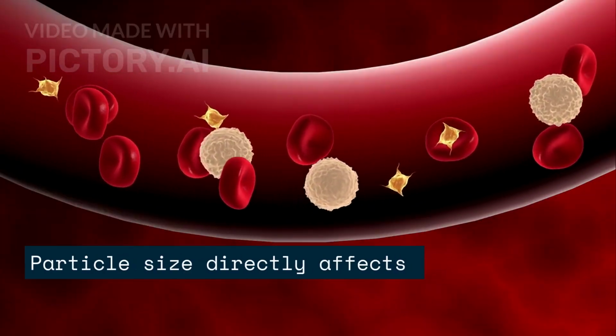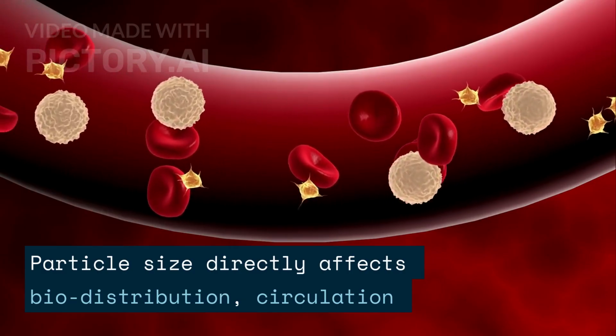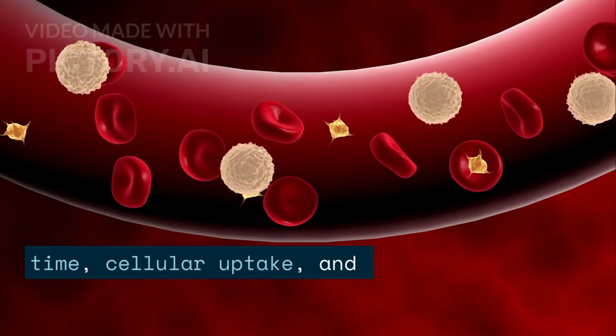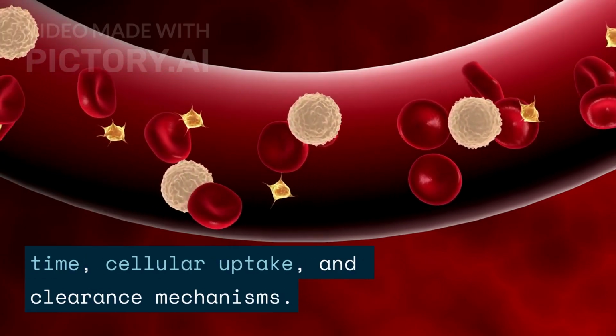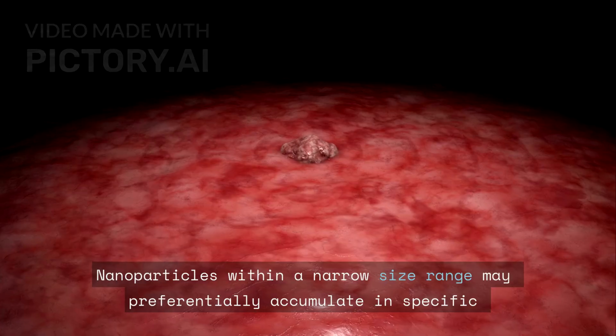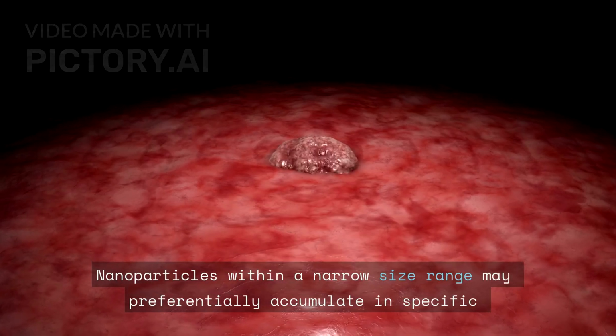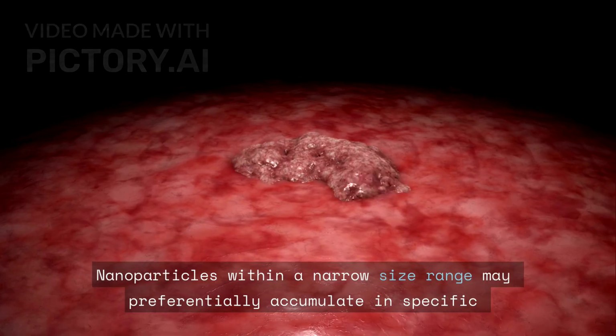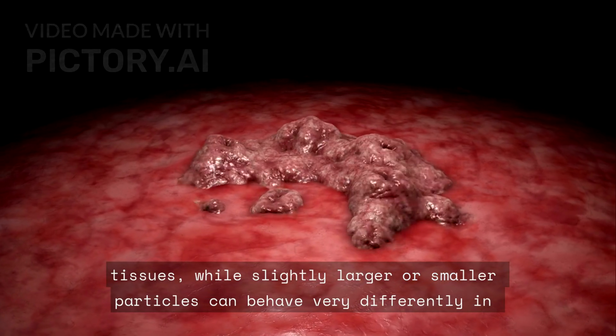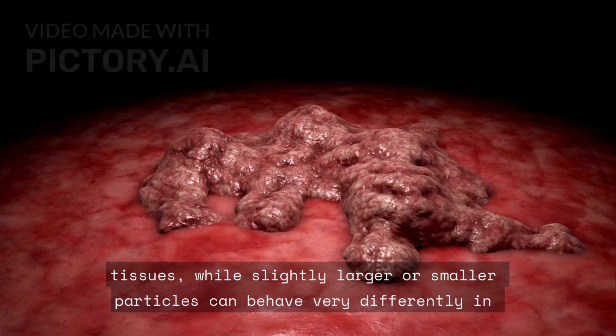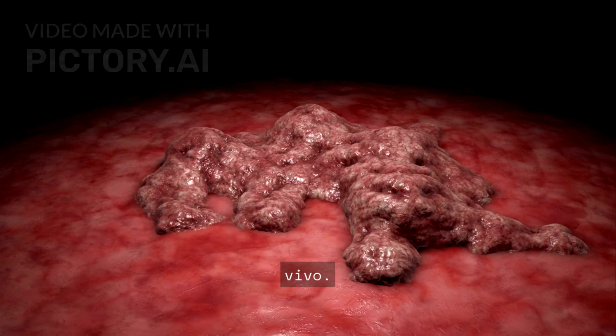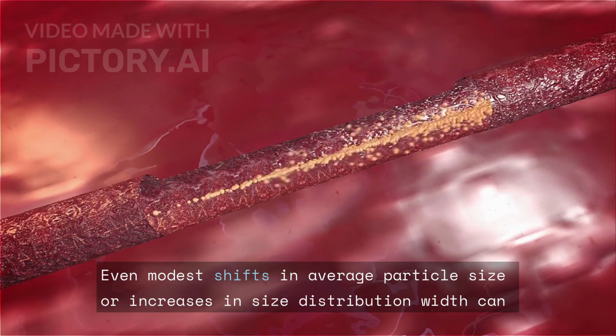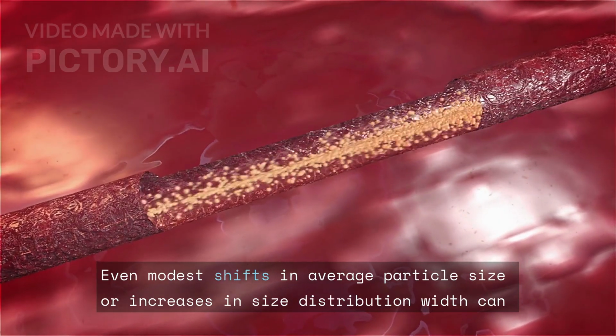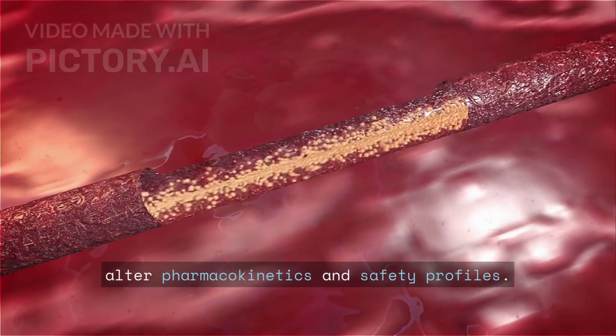Particle size directly affects biodistribution, circulation time, cellular uptake, and clearance mechanisms. Nanoparticles within a narrow size range may preferentially accumulate in specific tissues, while slightly larger or smaller particles can behave very differently in vivo. Even modest shifts in average particle size or increases in size distribution width can alter pharmacokinetics